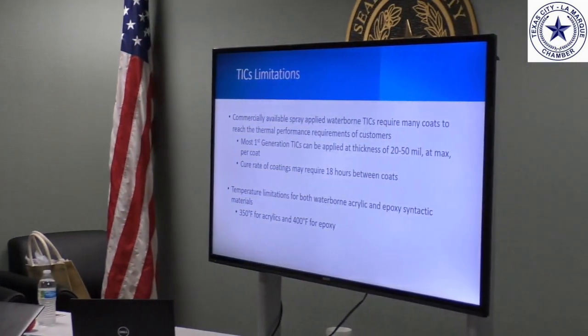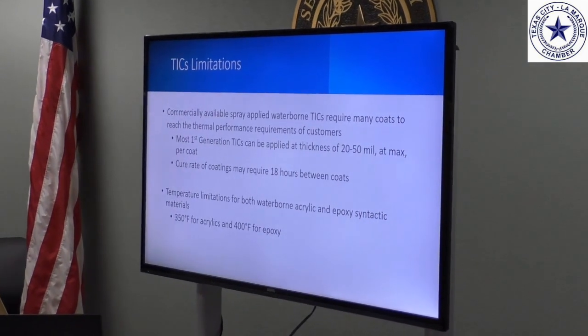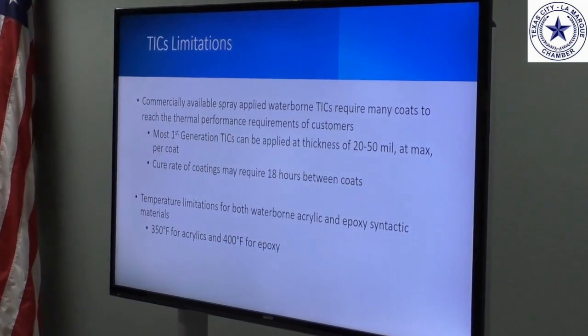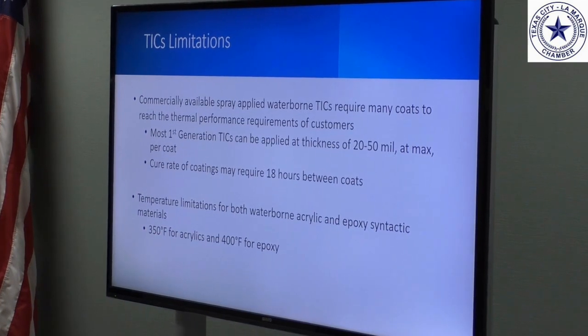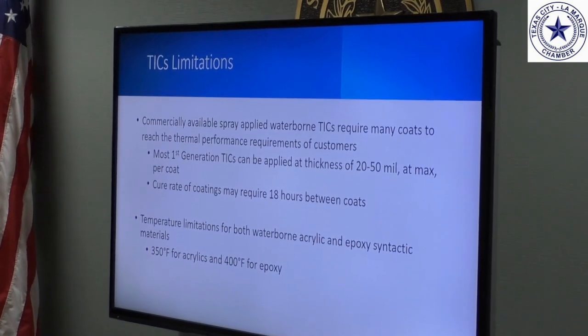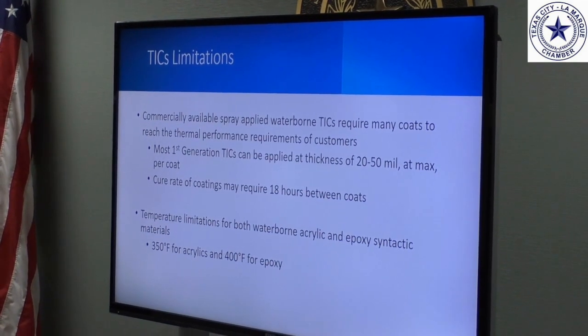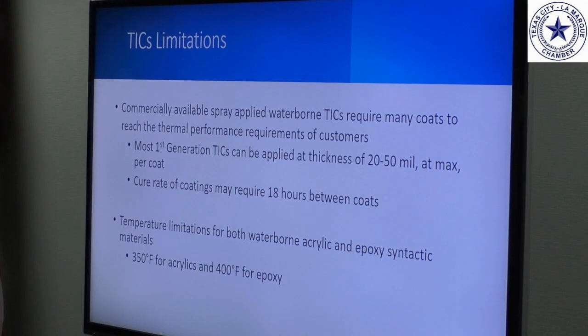There's also temperature limitations. These are polymeric materials, waterborne acrylics and epoxy syntactic material, with temperature resistance up to 350 degrees F for acrylics and 400 degrees F for epoxy. So there's limitations there in which you can apply the material. Some plants operate at temperatures higher than that. Some vessels and piping run temperatures of 500 degrees F. And so there's limitations where you would have to use material besides acrylic coating that we have to have thermal efficiencies and mitigate corrosion in those areas. But as you go higher up in temperature, CUI becomes less of a concern.